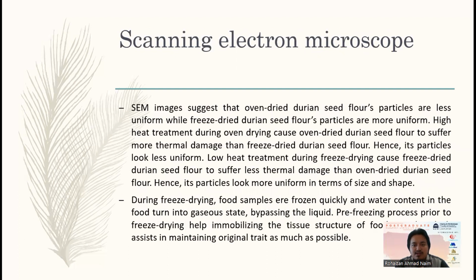SEM images suggest that oven-dried durian seed flour's particles are less uniform, while freeze-dried durian seed flour's particles are more uniform. High heat treatment during oven drying causes oven-dried durian seed flour to suffer more thermal damage than freeze-dried durian seed flour. Hence, its particles look less uniform. Low heat treatment during freeze drying causes freeze-dried durian seed flour to suffer less thermal damage than oven-dried durian seed flour. Hence, its particles look more uniform in terms of size and shape.